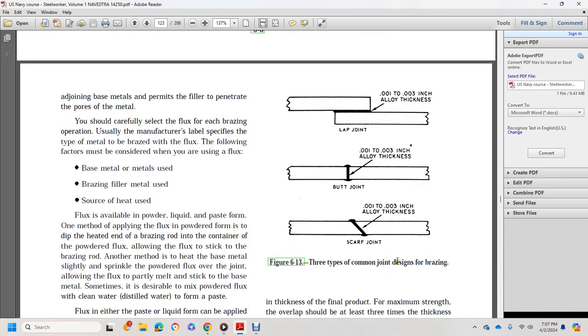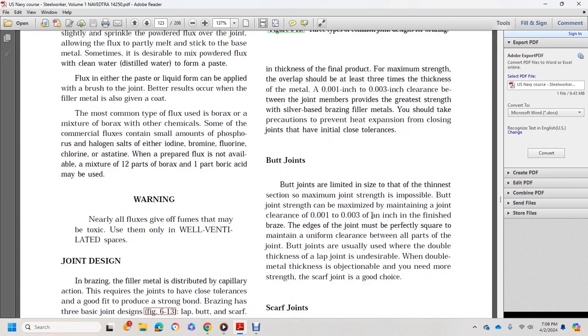Figure 6-13 shows the three types of joint design: a lap joint, a butt joint, and a scarf joint. Butt joints are limited to the thickness of the section. Maximum joint strength is possible in a butt joint by maintaining a joint clearance of 1/1000 to 3/1000 of an inch. The brazed edge of the joint must be perfectly square to maintain uniform clearance between all parts of the joint. Butt joints are usually used wherever the double thickness of the lap joint is undesirable. If more strength than a butt joint is needed, the scarf joint is a good choice.